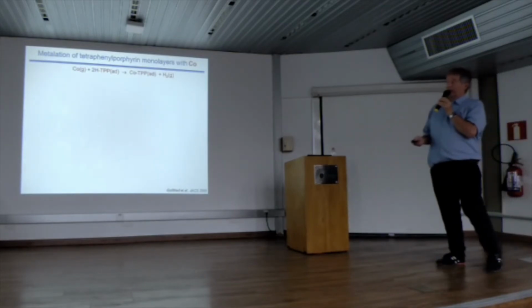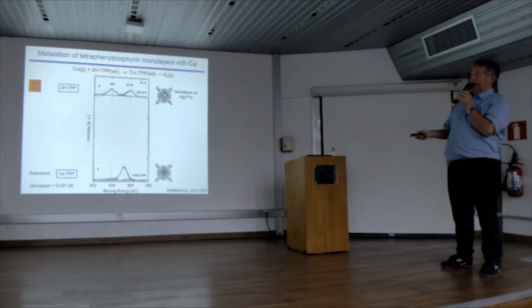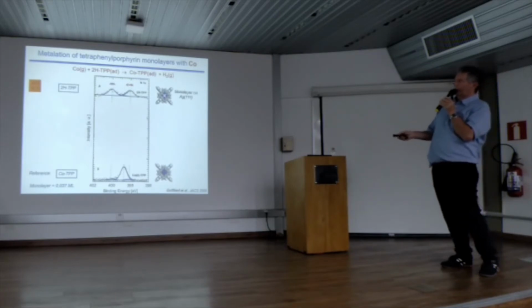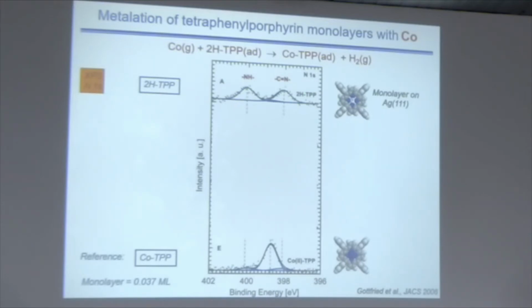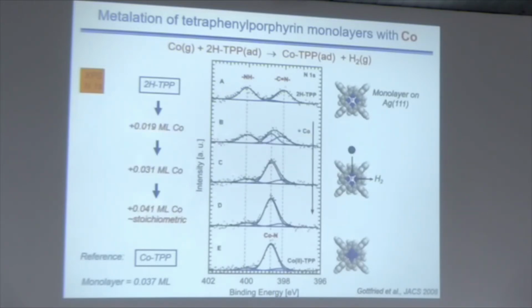And XPS is a very nice means of following it, because here I show the XPS spectra of this one you have already seen. This was the monolayer on silver, 2 eV separation here. The molecule doesn't interact with the substrate. Then down here, we add the metal atom in the center and deposit this to the surface, the intact metallated one, and you see only 1 peak. And the intensity here is 1 to 1. And if you add these 2 peaks in intensity, you get the peak of this height, but at a different binding energy. So this is our signature of the metallation. And then we take the molecule and then deposit the cobalt. And if you deposit the right amount of cobalt, so that you have exactly 1 cobalt per porphyrin, then you get exactly what you expect for the metalloporphyrin. So we can metallate on the surface.